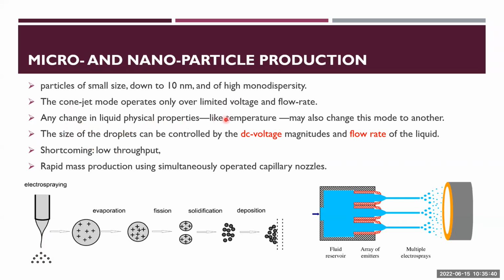Any change in liquid physical properties, like temperature, will change the mode. The size of the droplets is controlled basically by the high voltage and the flow rate of the liquid. The shortcoming, as we mentioned before, is low throughput because of the slow process. Rapid mass production can be done by simultaneously operated capillary nozzles, like in this setup and the one that we see in the first video, where you can operate several nozzles together. Using the same high voltage and the same pump, you design an array of emitters to increase the throughput of the spray.